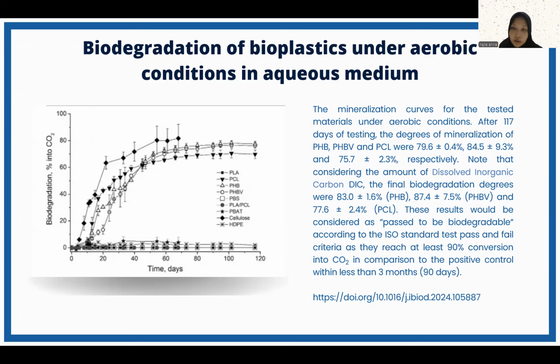So for the aerobic, the mineralization curve for the tested materials under aerobic condition after 117 days of testing, the degrees of mineralization of PHB, PHBV, and PCL were, for PHB, 79.6 plus minus 0.4%, and for PHBV, 84.5 plus minus 9.3%, and for PCL, 75.7 plus minus 2.3% respectively.